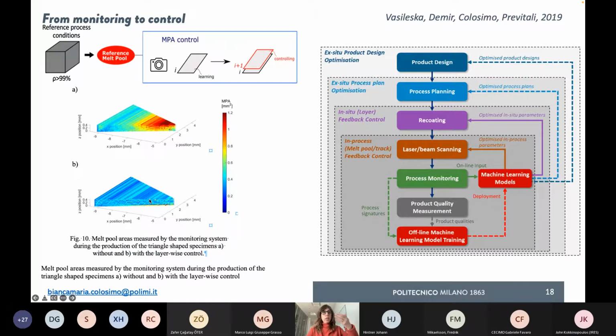So I'm looking at the ID of what I see. In this case, we were looking at the melt pool in real time, and we can recognize that the melt pool intensity is going to be too high in one specific location of the part we are printing. But what is new is that in this case, we didn't say just, okay, let's stop, because we saw that this red location means that the melt pool is delivering too much, the system is delivering too much energy in that specific location, and so the melt pool is revealing that something is wrong.